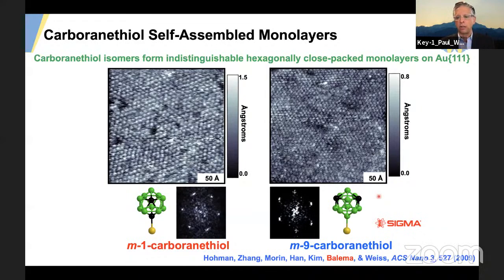So instead of those linear chains that I showed you earlier, which have flexibility and thus have what are called gauche defects, kinks that are dynamic in the system, and that have tilt boundaries on the surface that lead to another kind of defect, we realized that if we used upright, symmetric, rigid molecules, by symmetry we can remove most of the defects that are found in those self-assembled monolayers. So our favorite family of cage molecules that do that at the moment are the carboranethiols.